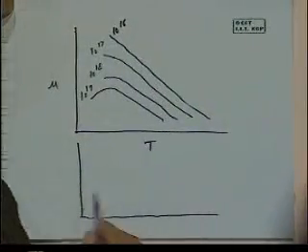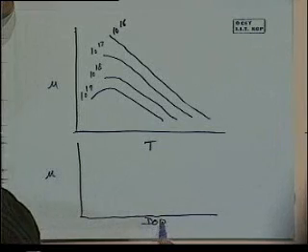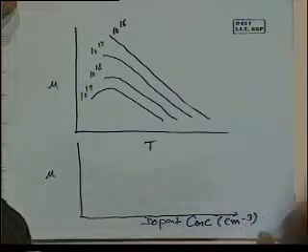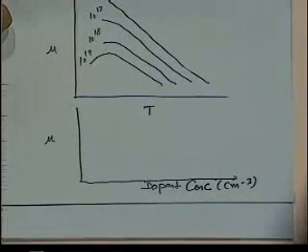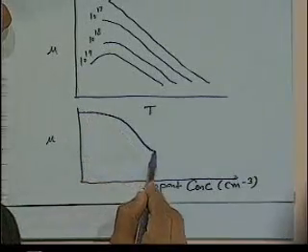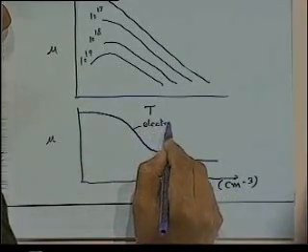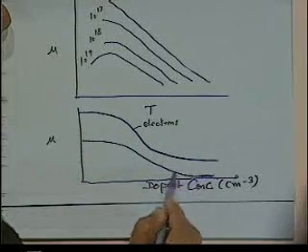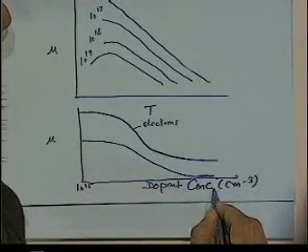People have also plotted, particularly for silicon, standard curves of mobility versus carrier (dopant) concentration. We can plot for both electrons and holes. The x-axis runs from roughly 10 to the power 15 to 10 to the power 20. Electron mobility in silicon at low concentrations is around 1500, and hole mobility is around 450 — those are the maximum values.